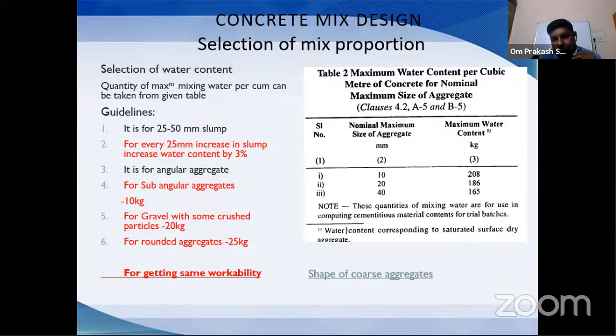Here the water content is given for 25 to 50 mm slump. It means for 20 mm maximum size aggregate, if we use 186 kg of water, we may get 25 to 50 mm slump. If our requirement is more than 50, then for every 25 mm we have to increase the water by 3%. Again, this water content is given for angular aggregate. If the aggregate is subangular, we can reduce 10 kg of water. If gravel is used, we can decrease the water by 20 kg. If we are using rounded river bed aggregate, we can reduce by 25 kg.